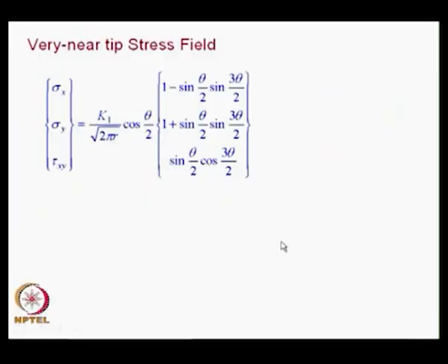When you have series terms, you normally think, okay, if I take the first term, the solution is to a certain level of accuracy. If I take several other terms, the accuracy keeps on increasing. That kind of generalization you cannot make here. The first term is still what you have in your conventional Westergaard solution. Now, we will also have a look at some aspects of the basic solution by Westergaard. Let us see what all we understand from the basic solution here.